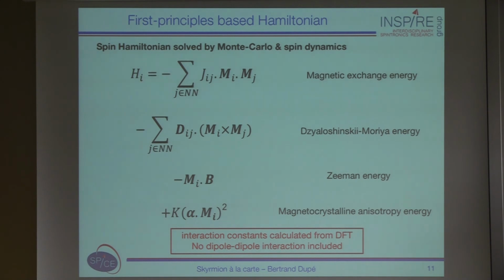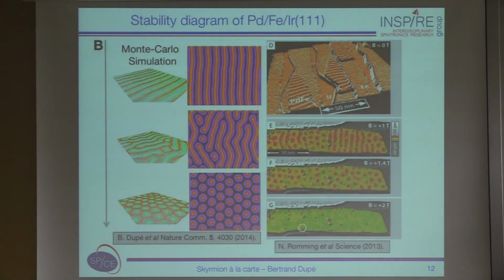So in order to convince you that it works, this is, I think, very similar to the slide that Kirsten von Bergmann showed a few days ago. So here is the palladium, iron, iridium with a spin spiral ground state. You apply an out-of-plane magnetic field.